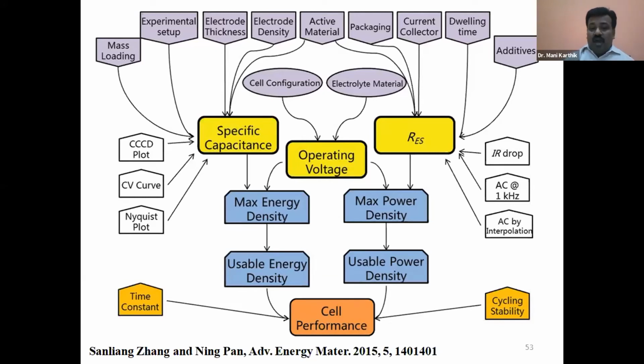If we see the operating voltage, cell configurations, and electrolyte material, as I said, the electrolyte is very important to determine the final voltage of the device. And if we see the resistance, ESR, equivalent series resistance, it depends on how much active material is loaded and the package of the cell, current collector, and also the dwelling time and additives. All of these create the resistance.